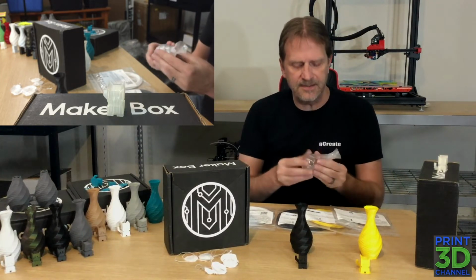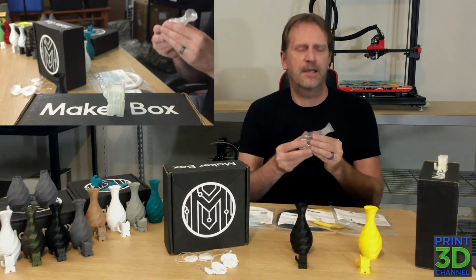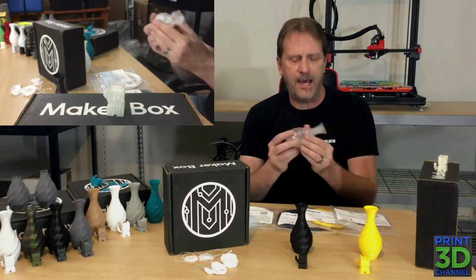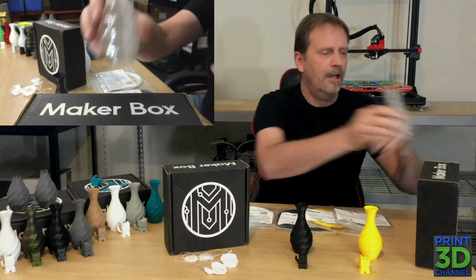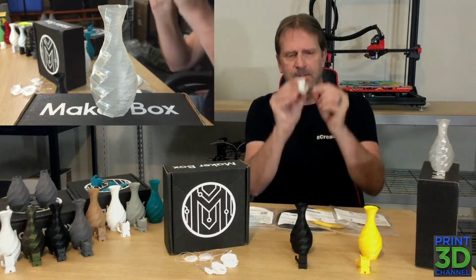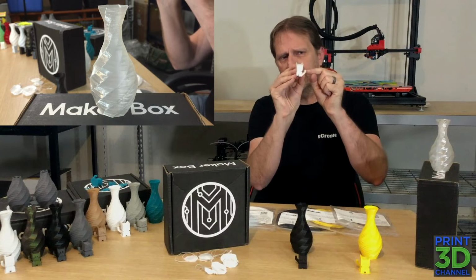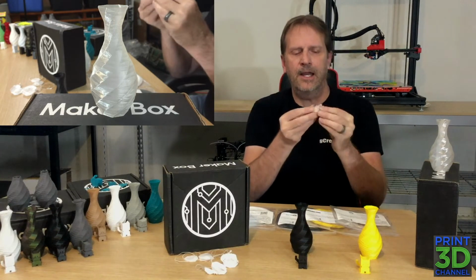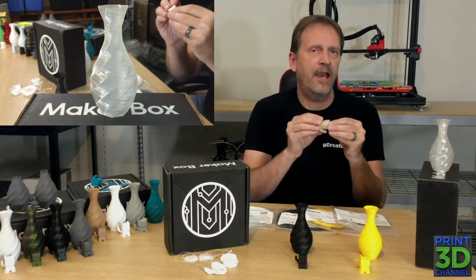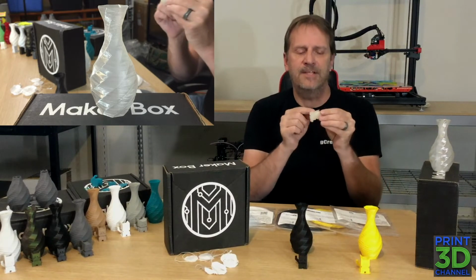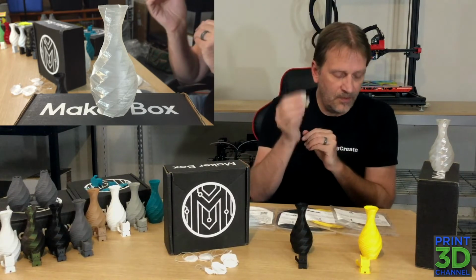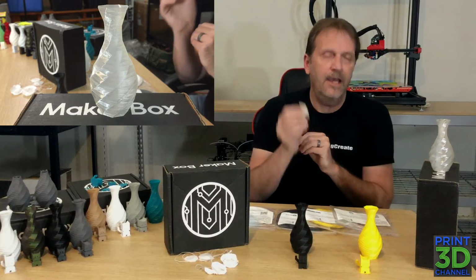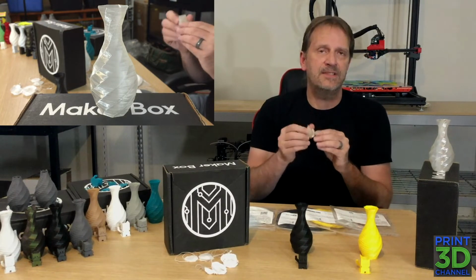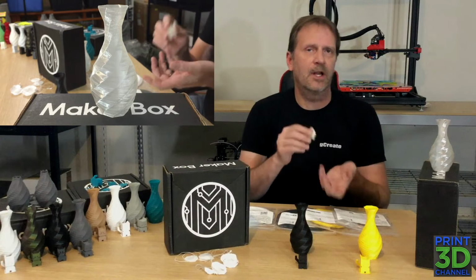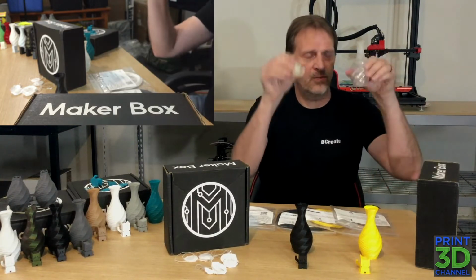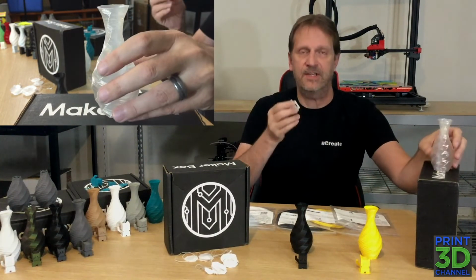I do like this. This has almost like a soda bottle plastic type of feel to it, a thin one at that, but it still has that feel to it. And the Cali Cat turned out awesome. There are just maybe 1 or 2 little string hairs between the tail and the body, and I didn't have any of the same problems that I normally have with printing the Cali Cat, but the temperature was so high because I printed this at 240 degrees C on my hot end, and I did ramp up the bed temperature to 60 C from 50 C, and then I did turn it up to 70 C between these 2 prints, so my maximum temperature printed was 70 C.